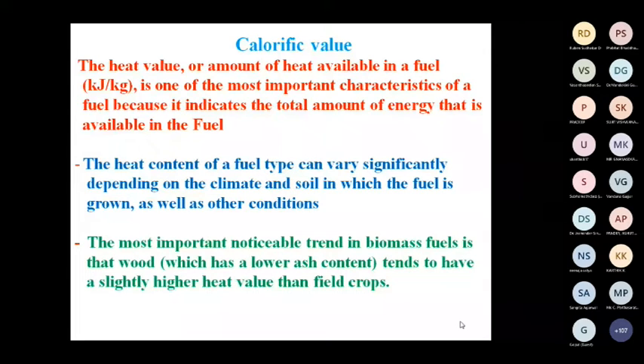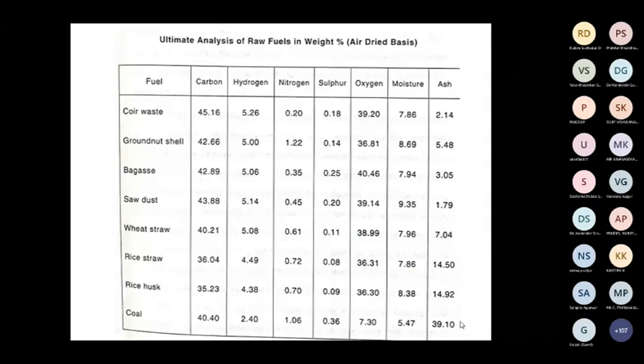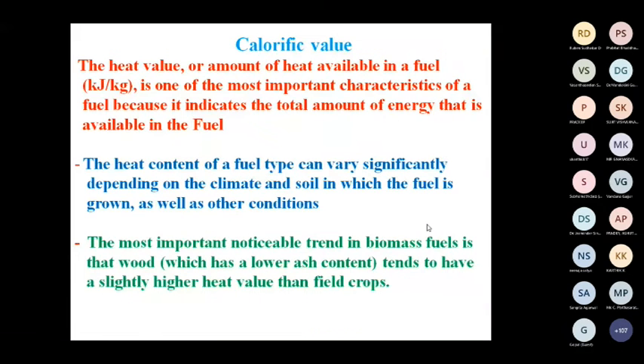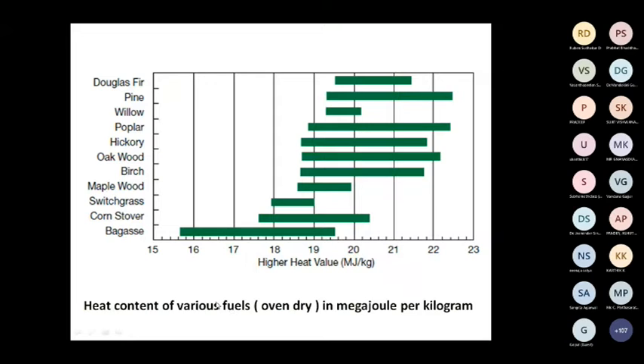The most important noticeable trend is that biomass fuel such as wood has very low ash content and tends to have slightly higher heating value than field crops. For example, in our analysis, sawdust has an ash content of around 1.79. Here is a picture of heat content for various fuels. Pine wood, poplar wood, and oak wood all have very high calorific value because of much lower ash content compared to grass, for example bagasse. So all the wood fuels have very high calorific value because of very much lower ash content.